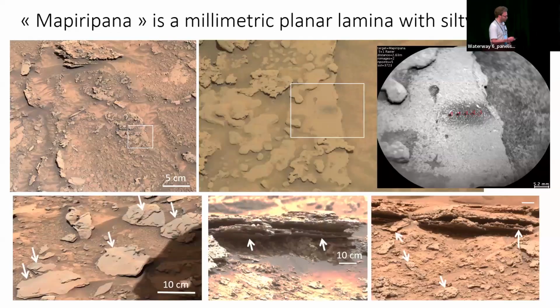So what does it look like? This is the facies of that target. The analysis was done on this planar surface here, which is pervasive to that block around. There is an assemblage that's typical: it's always surrounded by nodules that are on the lamina above. And the lamina itself is maybe composed of several laminae. Here you see them exposed as well, and possibly a couple of laminae are in this profile, this lithofacies. We've seen it also outcropping in the marker band itself.